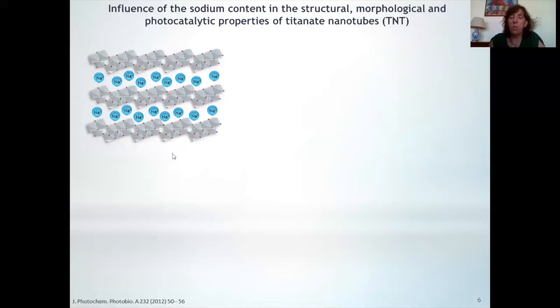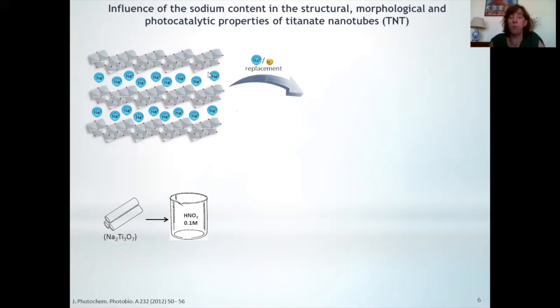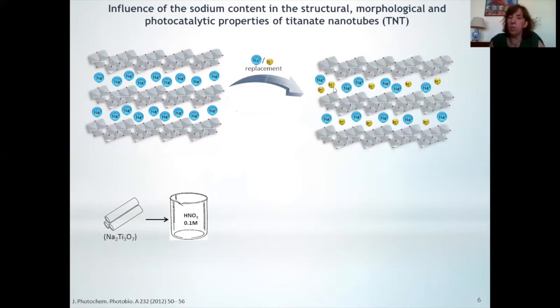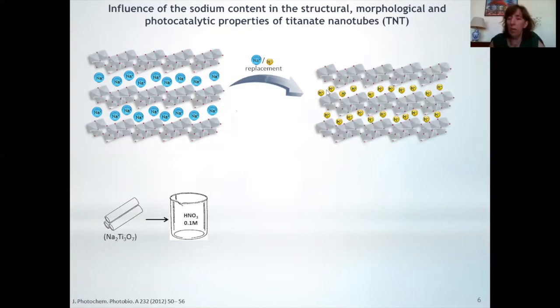So, what is the easiest way to modify these materials? We just need, for instance, to try to replace some of the sodium ions by H+. What do we need to do? We just need to put our material in an acid solution. We must be careful about the time and the concentration of the solution, and we will start to see the replacement of the sodium by H+. Of course, if we wait a little bit more time, in the end, we can have the total replacement of the sodium by H+.